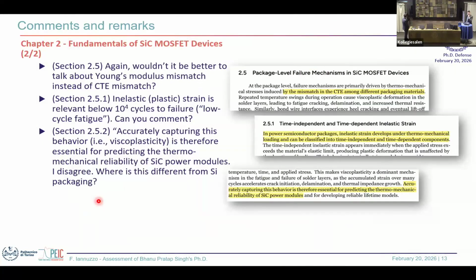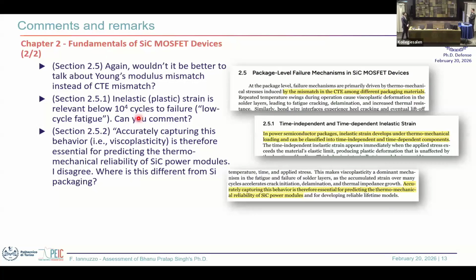Still chapter 2. Again, we discussed this, so I don't want to touch it anymore. Now, in my experience, this is quite general, not just related to chapter 2. Using the temperature swings you have been using, no matter PC min or PC sec, with your numbers, 145 maximum junction temperature, and I don't remember what your temperature swing was, in the range of 60 Kelvin or whatever, I get in the range of 100,000 cycles to failure. You have one order of magnitude less.